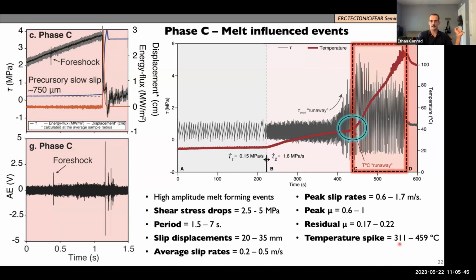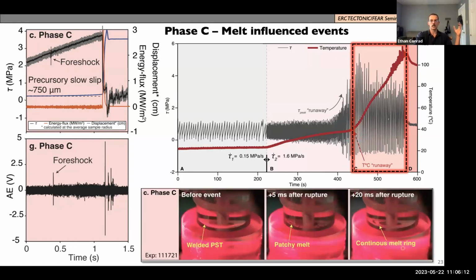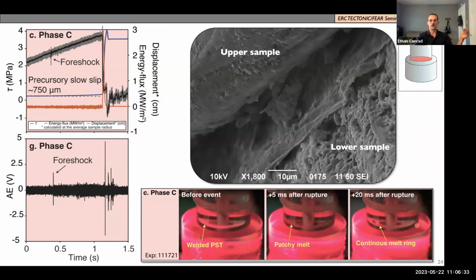The temperature spike is significantly higher. Using that formula that I showed before from Carslaw and Jaeger, it can be up to 460 degrees Celsius with each event. And that's a very short amount of time that you reach those temperatures, but you're melting a lot more, especially at the tips and at the micro scale, at the asperity tips and things like that. So it's really kicking off this feedback, and events are getting much larger. And in phase C, we can see this circular patch of welded pseudotachylyte before the event, and then after rupture, we can image the patchy melt forming and then coalescing into a continuous ring, leading towards later arrest.